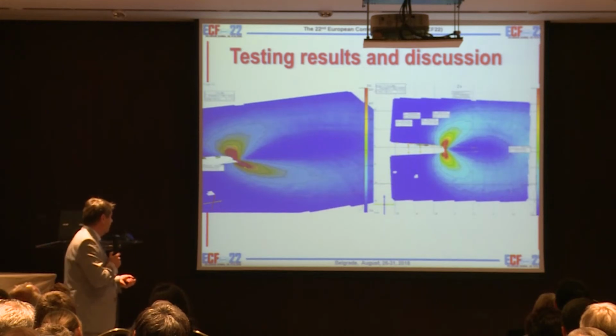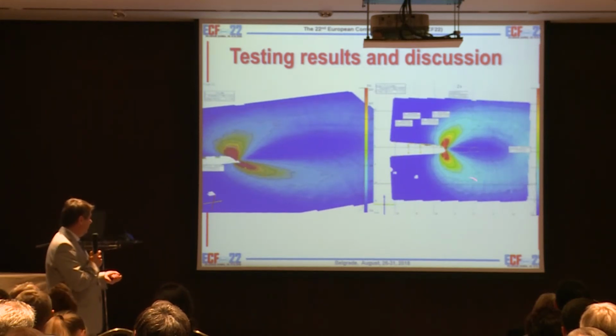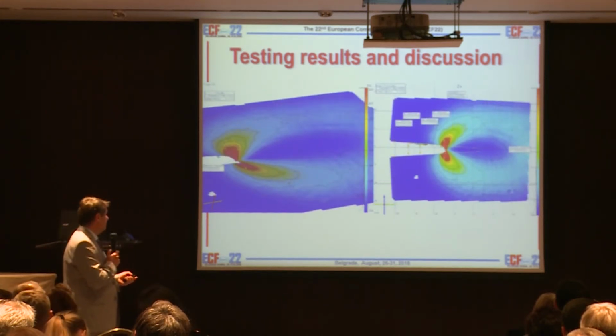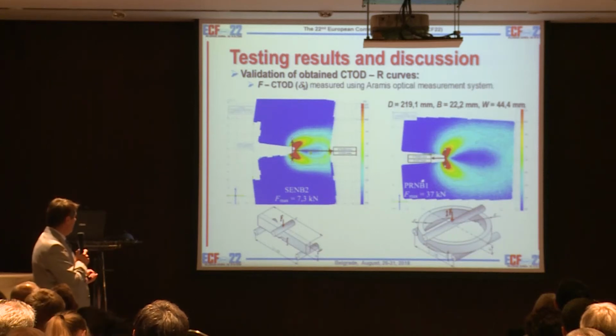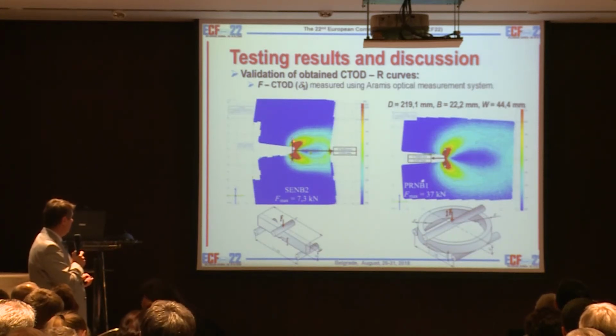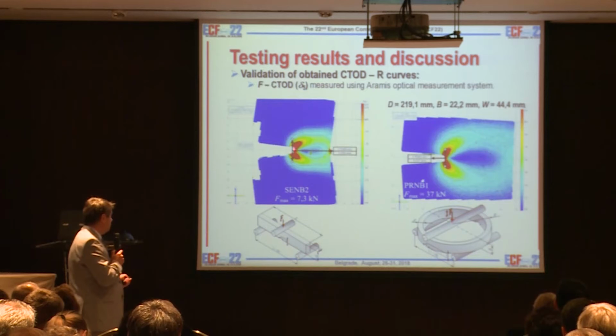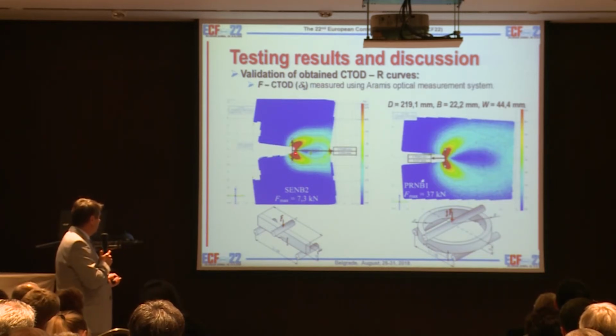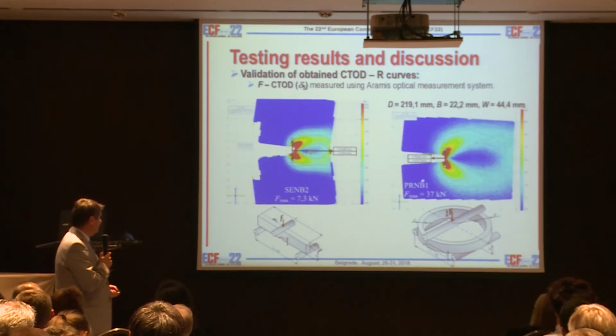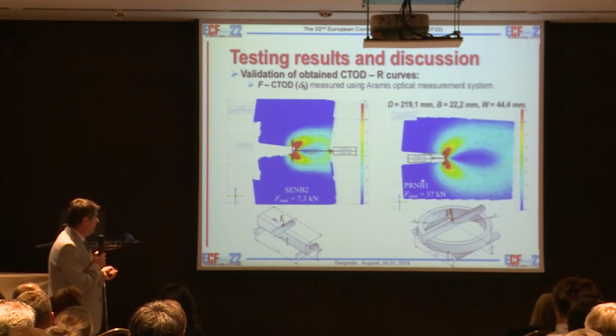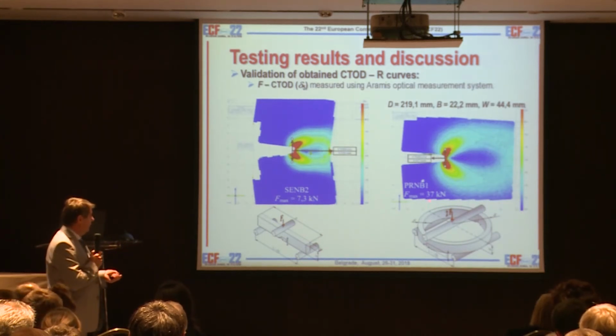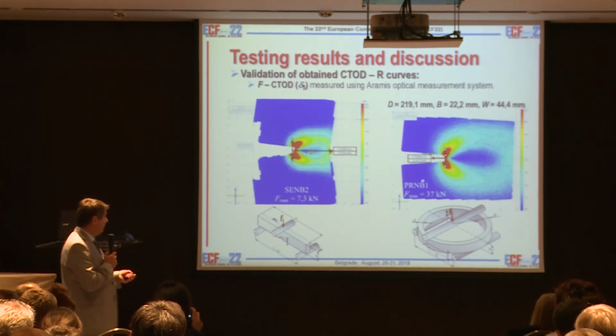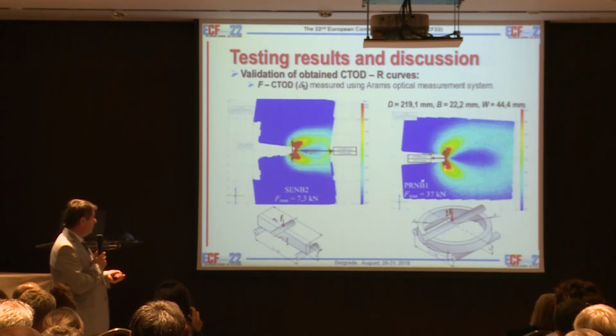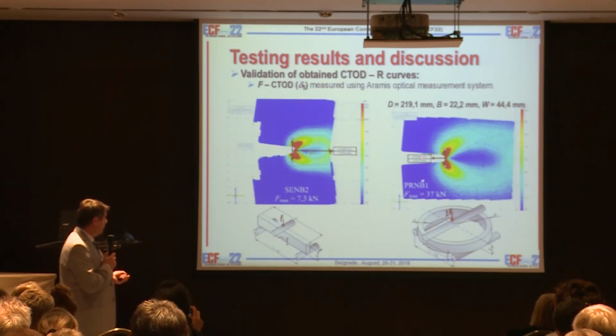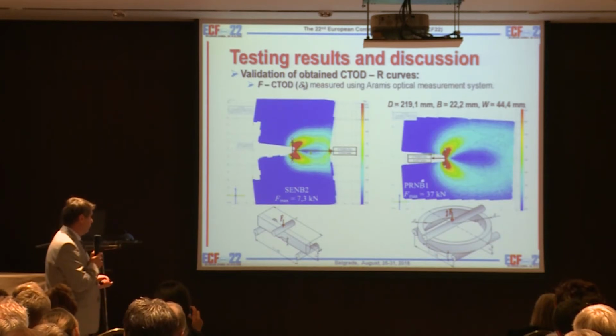With the equivalent strain of the crack made by RMS analysis. So now we have the point of crack initiation. We determined this delta 5 for the pipe ring specimen. It was of course 37 kilonewtons of force, and here you have the pipe ring specimen, and also in crack initiation it's a much higher force. It depends of course on the span distance, and we also get this delta 5 at the crack initiation point.